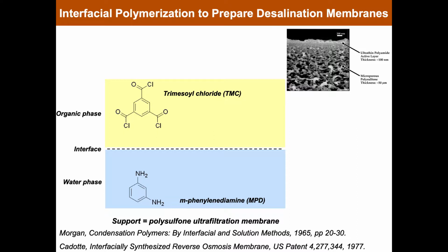These aromatic amines and acyl chlorides are violently reactive with one another, and so as these two layers contact one another, metaphenylene diamine and the trimesoyl chloride react almost instantaneously at that oil-water interface. And there is additional